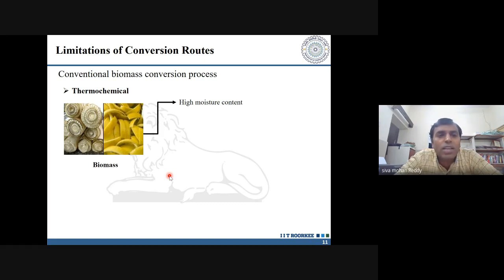If you look at the thermochemical processes, as I've already said, in the pyrolysis process we need to reduce the moisture content to less than 10%, to make sure that it is properly ground and then fed to the pyrolysis reactor, right? Now biomass which is rich in moisture, like agri residues, human waste residues, and all the animal residues, the fecal residues that you are talking about, are all rich in moisture content. So you need to provide additional energy to remove the moisture from the carbon sources, that is, the additional energy required to reduce the moisture content.